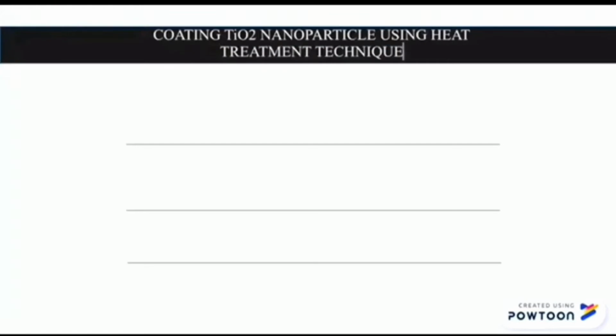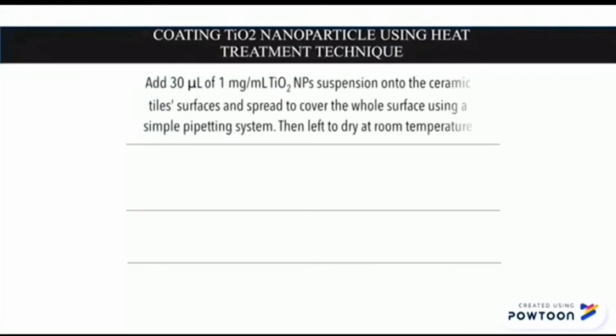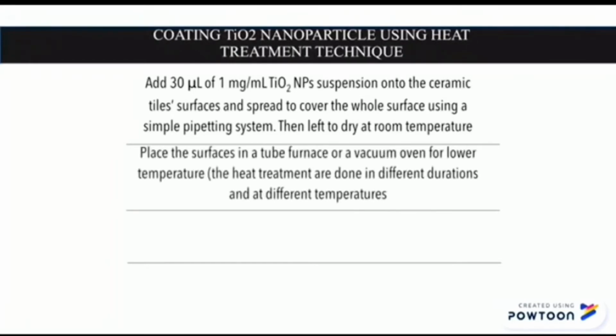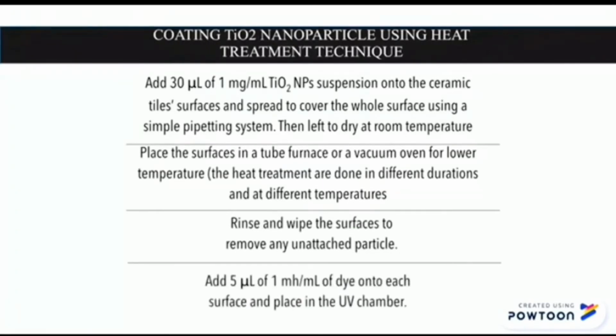Coating titanium dioxide nanoparticles using the heat treatment technique. First, add 30 microliters of 1 mg per 1 ml titanium dioxide nanoparticle suspension onto the ceramic tile surfaces and spread to cover the whole surface using a simple pipetting system, then leave to dry at room temperature. Place the surfaces in a tube furnace or a vacuum oven for lower temperature. The heat treatments are done at different durations and at different temperatures. Then rinse and wipe the surface to remove any unattached particles. Add 5 microliters of 1 mg per 1 ml of dye onto each surface and place in a UV chamber.